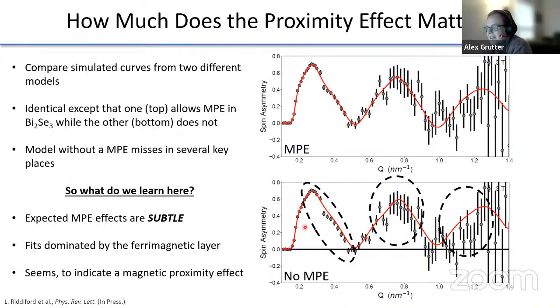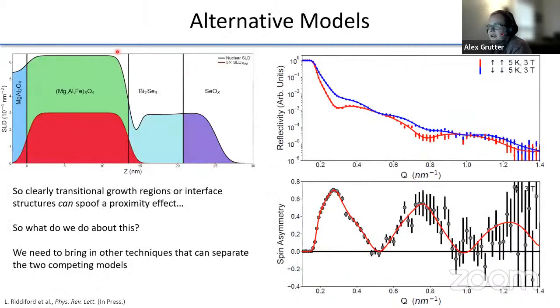But what do we really learn here? The proximity effects are very subtle signatures in the neutron reflectometry data, right? This, I think, doesn't always come through very well in the literature, but the signal you get is going to be overwhelmingly dominated by the large magnetization from the magnetized proximity reservoir, so the bulk ordered magnetic system. So while this seems to indicate a magnetic proximity effect, we need to look for subtle alternative models, like subtle changes to the model that might give us the same quality of fit without a magnetic proximity effect. And we can find one almost immediately. In fact, I think this was our first guess: what if the bismuth selenide has a bit of a weird transitional growth region of lower density at the interface?